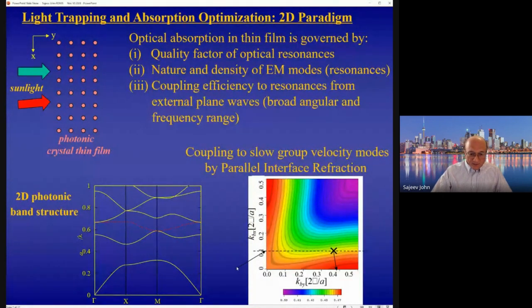So light that is coming in at a particular direction, say by this black arrow, finds a surface of constant frequency corresponding to that same frequency, and the direction of propagation of the light is in the direction of the group velocity of light, which is perpendicular to the isofrequency surface. So the light is deflected in the direction shown by this black arrow. So it would actually be deflected in a direction that is parallel to the interface. That further extends the dwell time of light. So it's not just going straight through and out, it's being deflected nearly parallel to the interface.